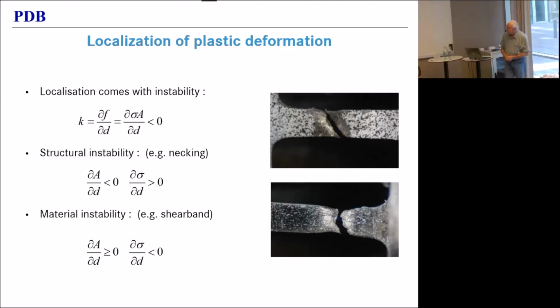So what happens when we localize? Well, when we localize, there is inevitably what I call an instability. You see a negative slope in the force displacement curve. So you get a negative stiffness. I call that an instability, not everybody does.